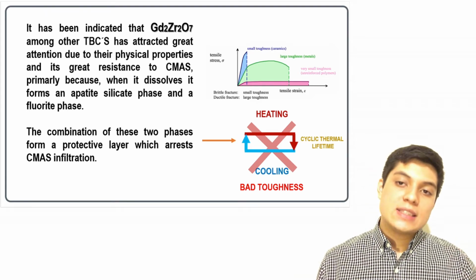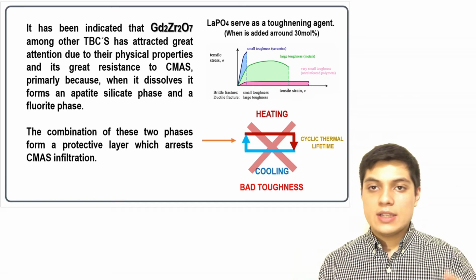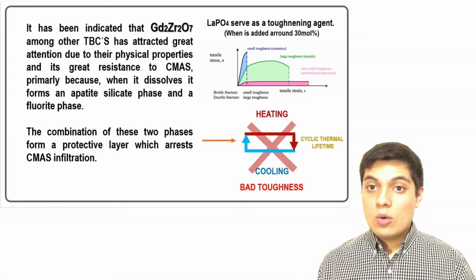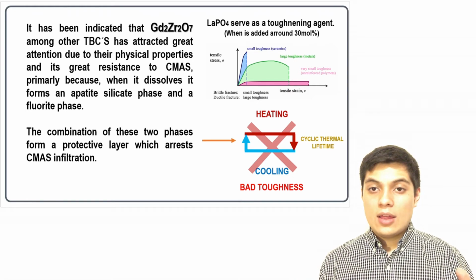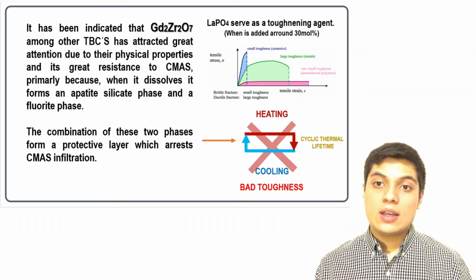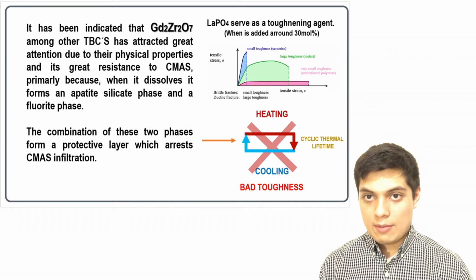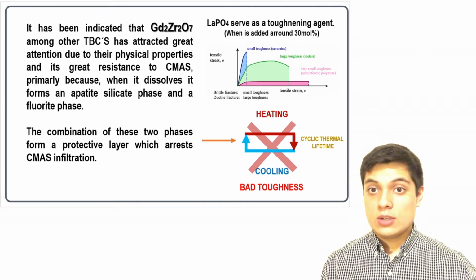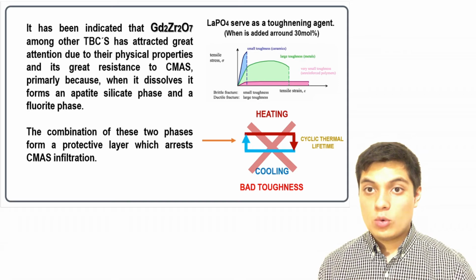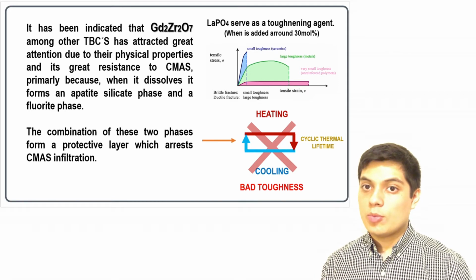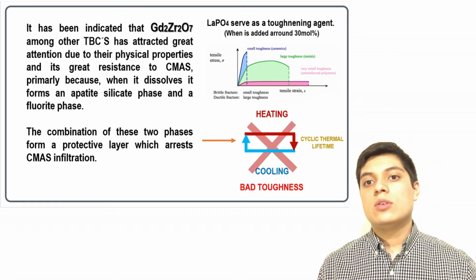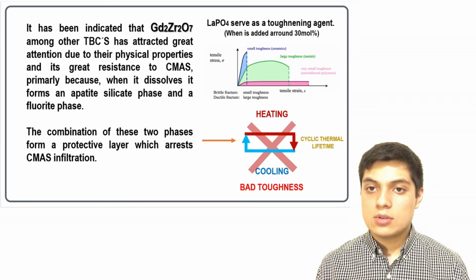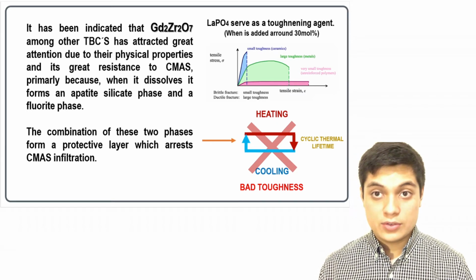But lanthanum phosphate can serve as a toughening agent when it is at around 30 mole percent. And an interesting fact about this percentage is that when you are going to prepare 1 kilogram of gadolinium zirconium oxide, you will need 167 grams of lanthanum phosphate.